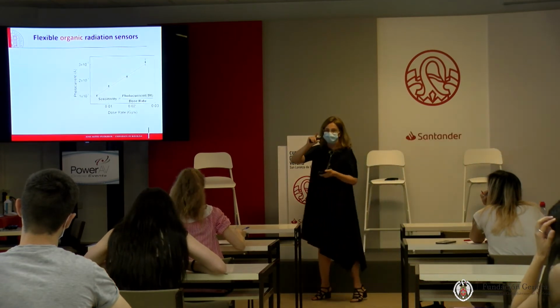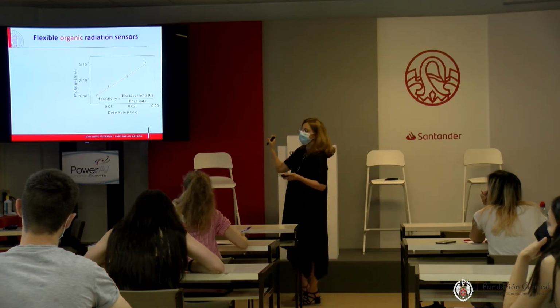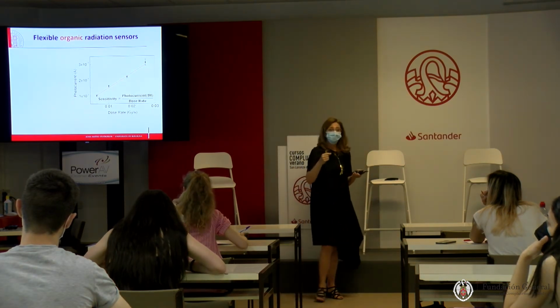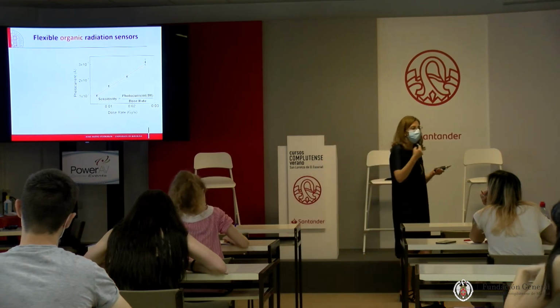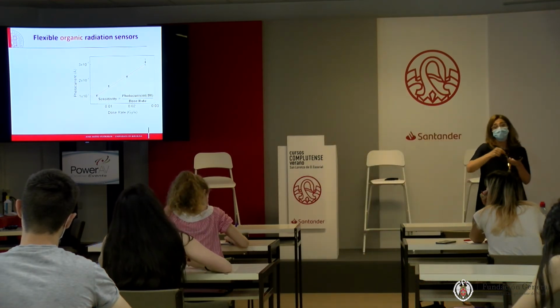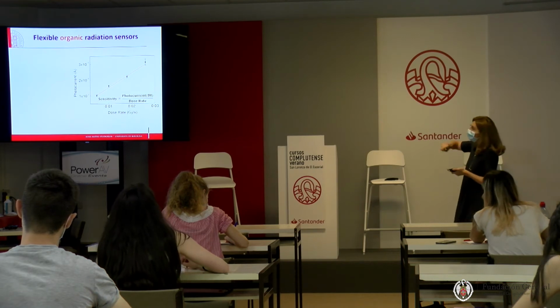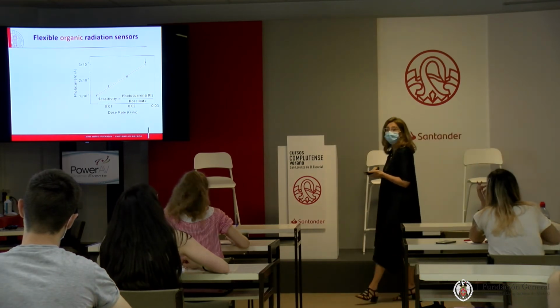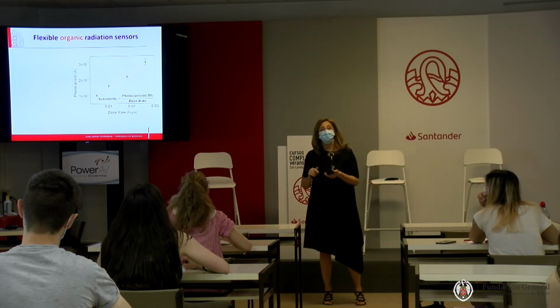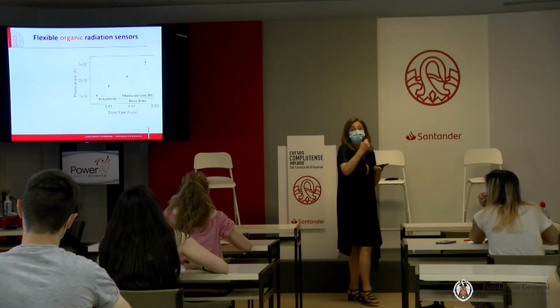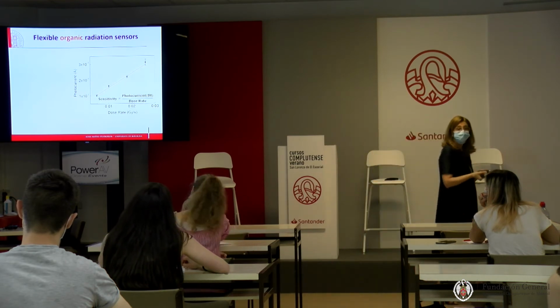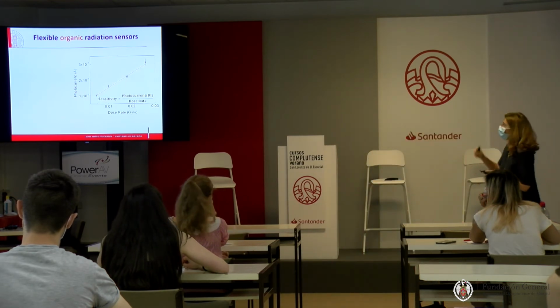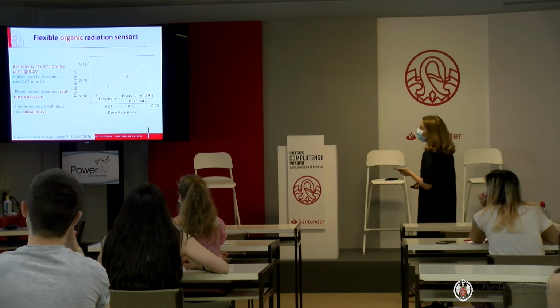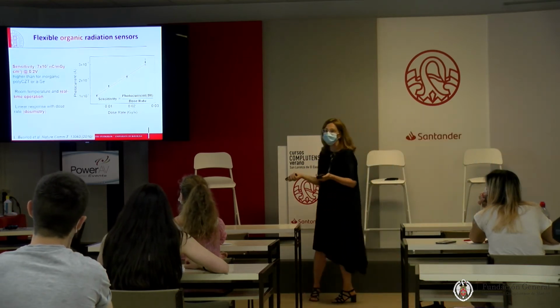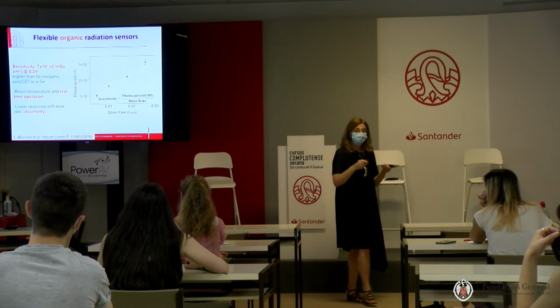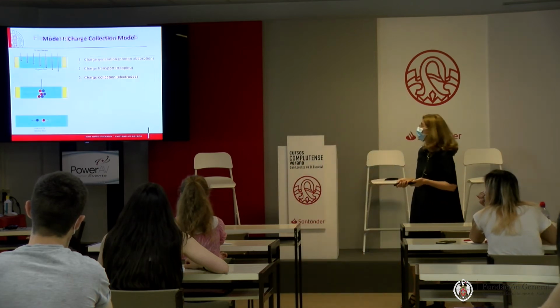The delta I, this photocurrent, is typically reported as a function of the dose rate, which is the flux of photons that is hitting the sample. So we change the flux of photons. And if the line is linearly increasing, we can say that this device can be used as a dosimeter because the response scales linearly with the incoming dose. The slope is called the sensitivity. And this is really interesting because it's what you need to assess the suitability of the material in the device to be used for X-ray detection.